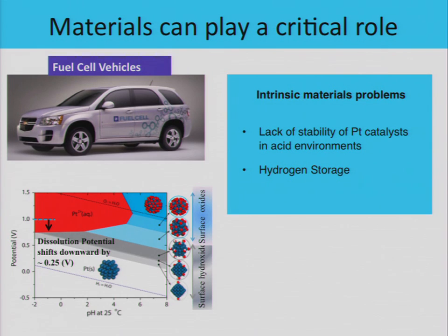And platinum tends to be very noble if you have a big bulk of it. It actually resists most of the dissolution, even at pH 0, which is as low as you can get pretty much. We can even go down to -2, but then you have more protons in your bath than water, so the pH scale kind of breaks down. This is the dissolution region you get if you have a 2 nanometer platinum particle.